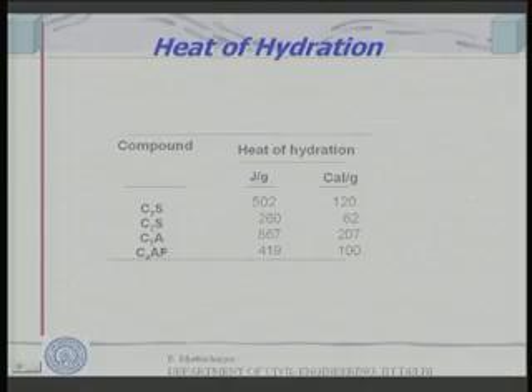So, the reaction is exothermic, produces heat, and if we see the relative heat produced by different compounds, we will see that C3S produces about 502 joules per gram. It should be, and this is 120 calorie per gram. This should be joules per kg. C2S produces 260, C3A produces 867, and C4AF produces 419. So, this is a relative heat of hydration, and C3A produces the maximum heat of hydration. It generates maximum heat on reaction, whereas C2S generates the least. C4AF is the next, and so on.